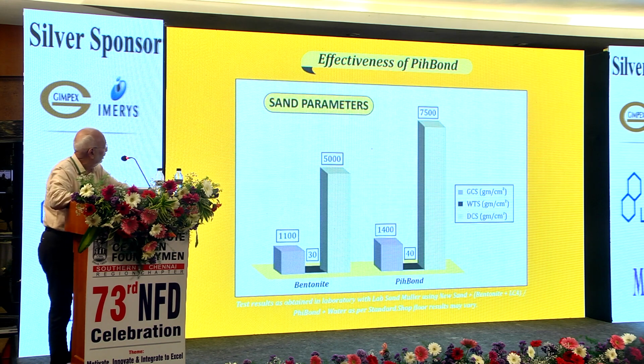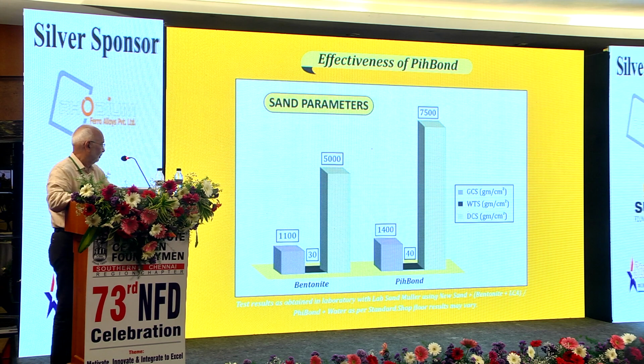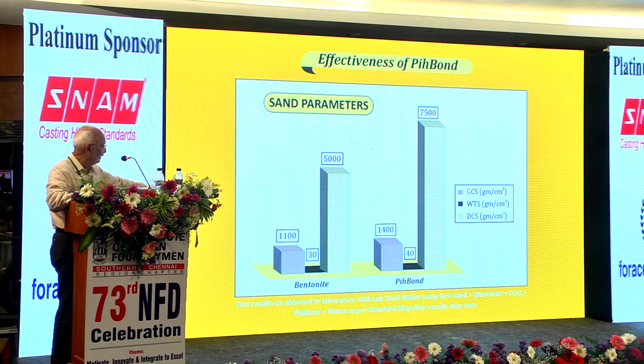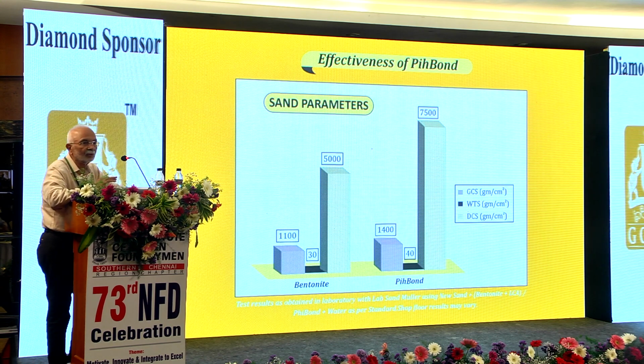Now, the sand parameters, effectively, with bentonite, the GCS is like this: 1100, 1400. The WTS 30 and 40, whereas the DCS goes from 5000 to 7500, which is an enormous jump, especially in the DCS.